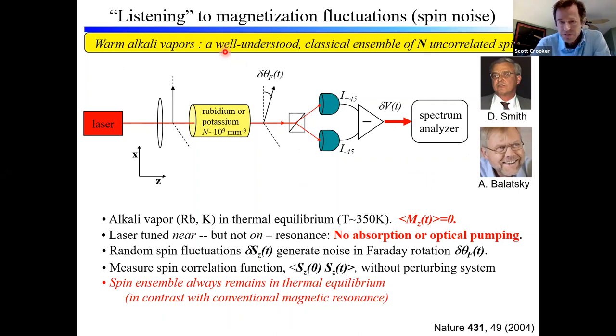And what we started with, the first demonstration, was embarrassingly simple. We were looking at warm, essentially room temperature alkali vapors. And this is a very well understood classical ensemble of N uncorrelated spins. So we just had a little vapor cell full of rubidium or potassium in thermal equilibrium. So there's no polarization here. The magnetization was zero on average.